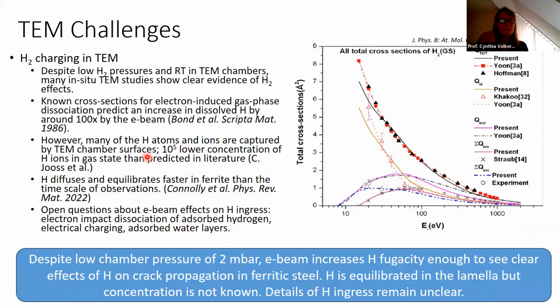We think things that need to be considered are the fact that we charge these specimens because of the secondary electrons that get emitted. The specimens become charged. There very often is a layer of adsorbed water on the surface. We haven't considered yet the possibility of the electron impact causing dissociation of adsorbed hydrogen that's already on the surface of the specimen. Those things have all not been considered. So we may have electron beam induced dissociation at the surface, maybe changing that and making it easier. We may have electrochemical effects simply due to the water layer there and the potential of the specimen.